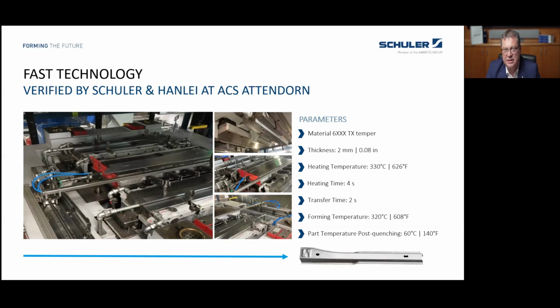And we had from our tech center in Göppingen, we still had our test die, which was a 3-station die for hot stamping. So we rebuilt this die, and as you can see in the left picture, with a heating plate, a small transfer unit within the die, and so we got this into operation. We did the trials at the Automotive Center Südwestfalen in Attendorn in Germany, where we rented a Schuler press. In this case, it was a servo press. And we did a lot of trials with different setups, with different materials, with different lubricants. Also, some OEMs were already participating who were interested in this process.